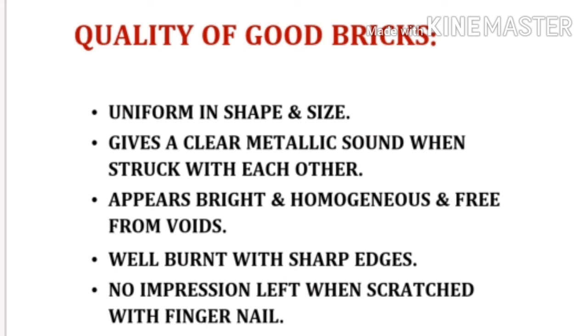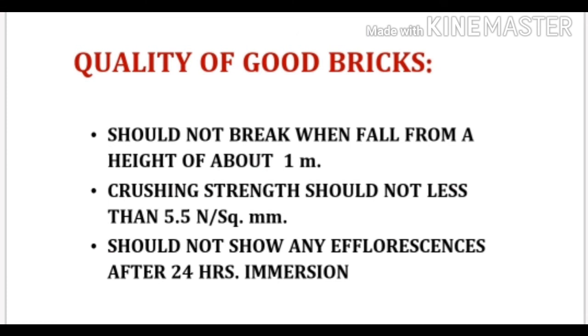Quality of good bricks: Bricks should be uniform in shape and size. They should give a clear metallic sound when struck with each other. They should appear bright and homogeneous and free from voids. They should be well burned with sharp edges and no impression left when scratched with a fingernail. They should not break when dropped from a height of about 1 meter. Crushing strength should not be less than 5.5 N/mm², and they should not show any efflorescence after 24 hours of immersion.